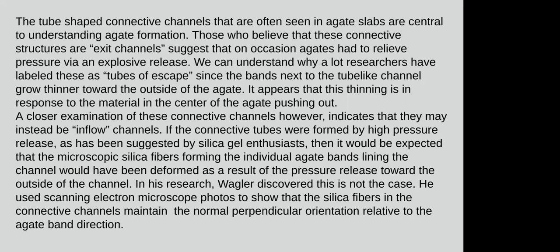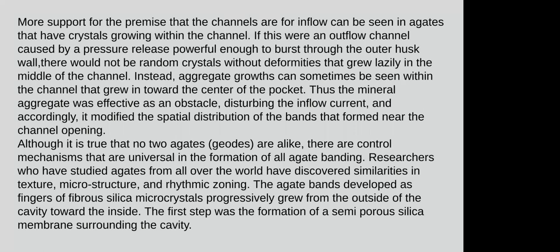A closer examination of these connective channels, however, indicates that they may instead be inflow channels. If the connective tubes were formed by high pressure release, as has been suggested by silica gel enthusiasts, then it would be expected that the microscopic silica fibers formed in the individual agate bands lining the channel would have been deformed as a result of the pressure release towards the outside of the channel. In his research, Wagler discovered this is not the case. He used scanning electron microscope photos to show that the silica fibers in the connective channels maintain the normal perpendicular orientation relative to the agate band direction. And I've got some real good pictures of that coming up.